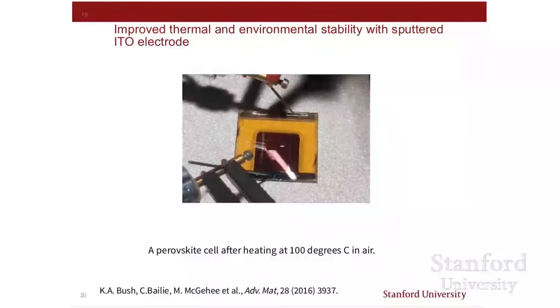And when we did that, we would put these solar cells on a hot plate in air at 100 degrees. And if you look at the picture here, you'll see the square in the center. That's where the ITO is. And there, the perovskite maintained its color. But outside of that, where there was no indium tin oxide, we found the material very quickly converted to lead iodide as the methyl ammonium left the film. So this demonstrated that the ITO would hold the methyl ammonium in, and moreover, we found that iodine doesn't seem to react with the indium tin oxide, and so we could run this solar cell in air with no packaging for a week on a hot plate at 100 degrees under one sun illumination. So this was a very big breakthrough, switching away from metals to using the indium tin oxide electrode.